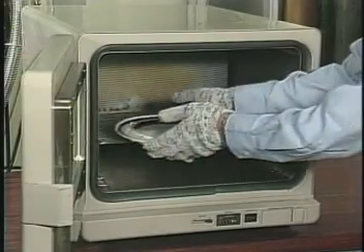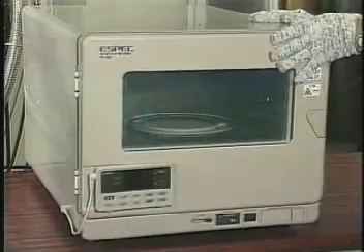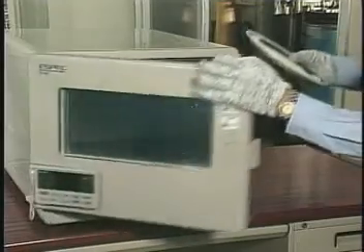In-line manufacturing operations, however, are best served by the low temperature curing sealant, which oven cures at 80 degrees centigrade in 2 to 10 minutes, and then is immediately available for the next step in production.